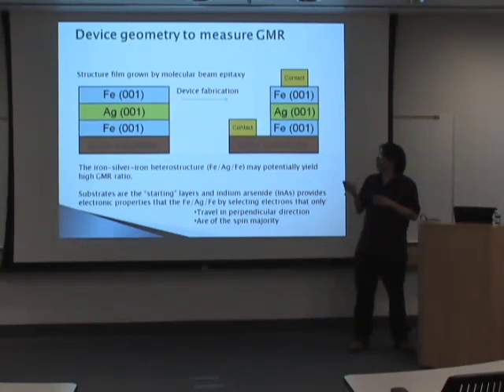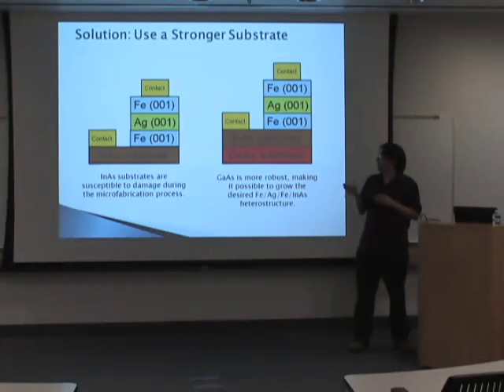Unfortunately, during the fabrication process to make this particular structure, indium arsenide tends to break. It just fails, so you can't really use it. And so instead, what you do is you start with gallium arsenide, and then you put on indium arsenide and the rest of the head. And gallium arsenide is much more robust, so it could survive the microfabrication process. Unfortunately, there's another problem. Growing indium arsenide on gallium arsenide is pretty rough, and I literally mean it's rough. You get roughness on the indium arsenide layer. So this part is the focus of this experiment.